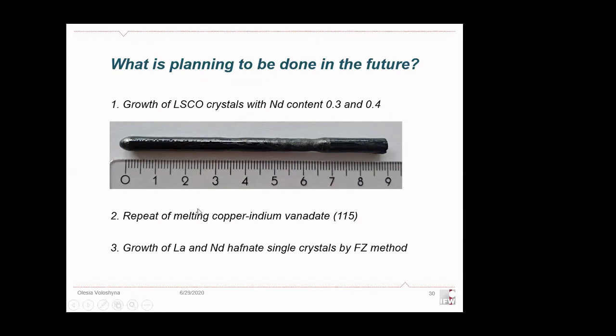The second is a repetition of the melting of copper indium vanadate with stoichiometry 1:1:5. So we have some ideas how to improve this. Instead of using the stoichiometric mixture, I'd like to try the pre-synthesis of the single phase and then try to melt it. Maybe we obtain something interesting. And the growth of lanthanum and neodymium hafnate crystals by the floating zone method.